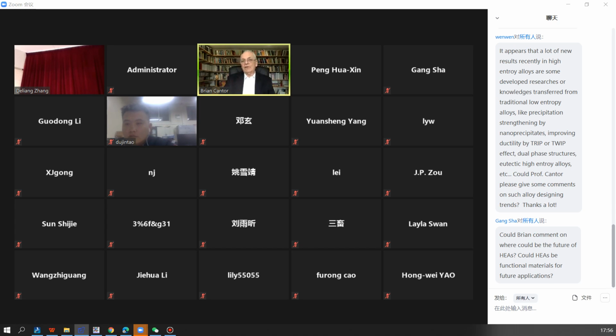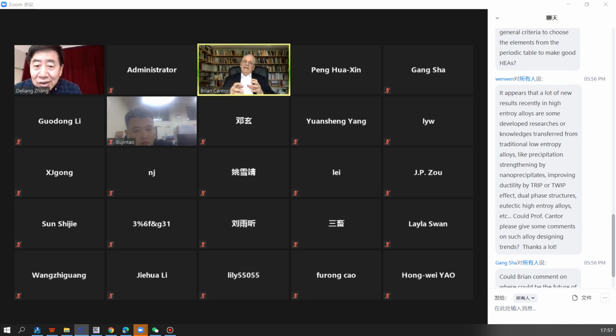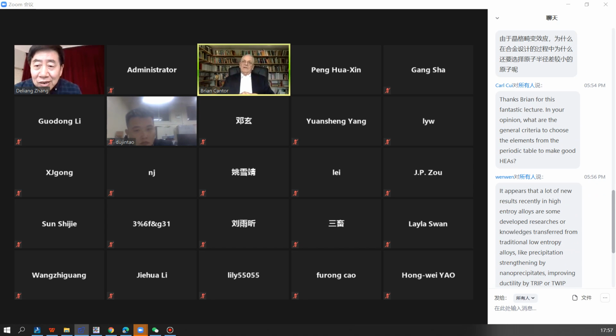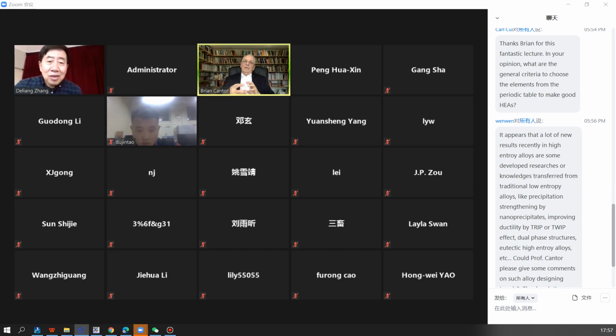Initially, you can use that to give precipitation hardening, but only very sensitively. If you do it too much, like we know in binary alloys, you get a brittle lot of intermetallics, and the material becomes brittle and unusable, or you lose the properties. So it's a subtle thing. We want to have those lattice strains, and some difference in the size of the atoms, and some enthalpy of mixing, but we want it small enough to create some of the special properties, yet small enough that it doesn't break the single phase structure, because then we get into other problems.